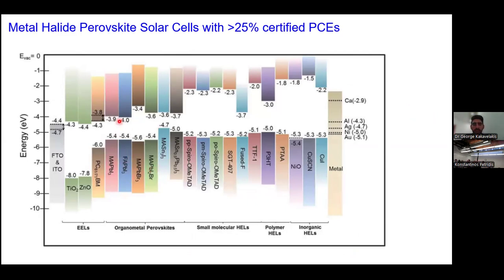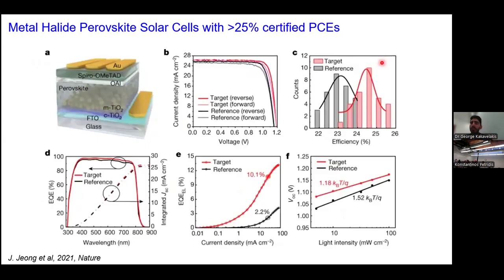And as you can see in this energy map, by engineering the materials, these are the perovskites here, and by engineering the different anions and cations, we can tune the bandgap. You see, we have 1.5, 1.4, even wide bandgap, 2.2, and you will see why these materials are very beneficial, even the wide bandgaps, later on. So by tuning this composition, we can fine tune the energy bandgap depending upon the use of the device. And now I mentioned 15% for the dye-sensitized solar cell. Nowadays, the state-of-the-art perovskite solar cell has surpassed 26% power conversion efficiency.